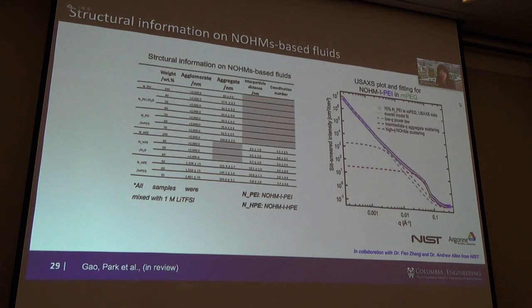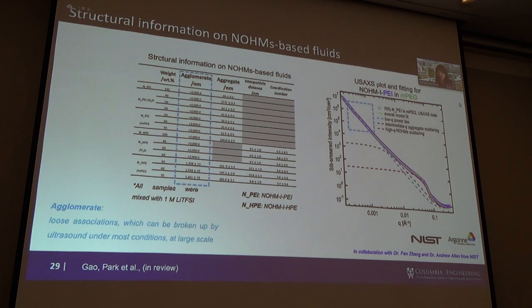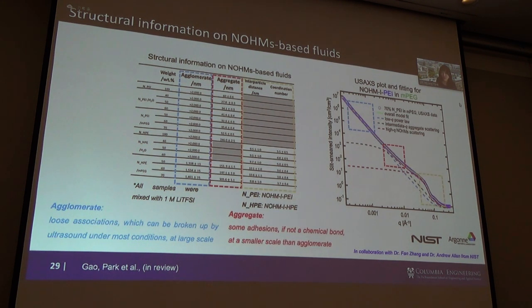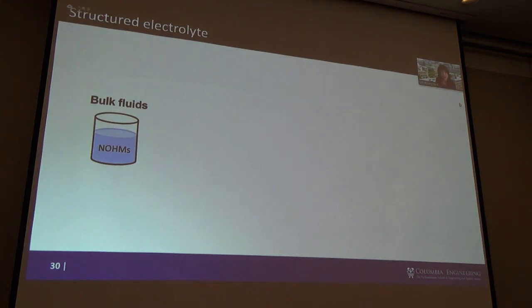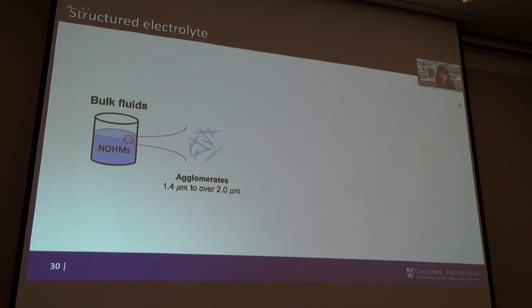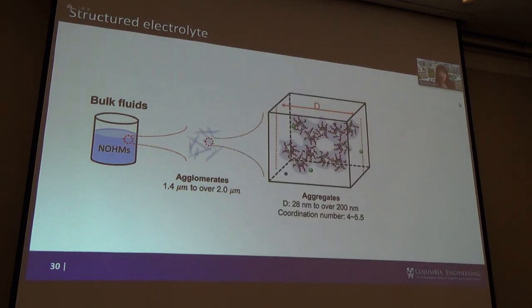So we went to the Argonne National Lab, did the USAXS testing, and then we found out that there's quite a bit of signal coming out in the low Q range, suggesting that there are much different length scale materials that exist. In fact, much chunkier stuff. So looking at all these data, this is what we think. The NOHMs is bulk, a very clear fluid, but then if you zoom in, there are agglomerates of these materials. And then if you zoom in even further, there are tens to 100 nanometer aggregates.